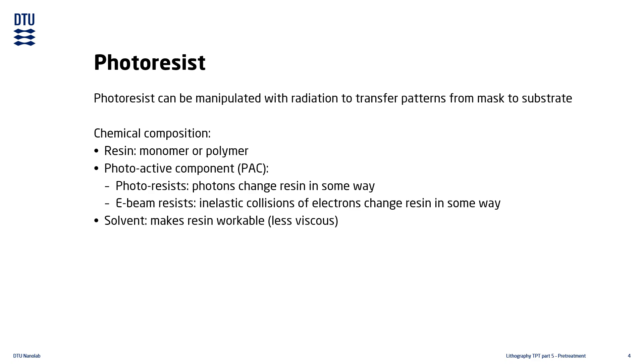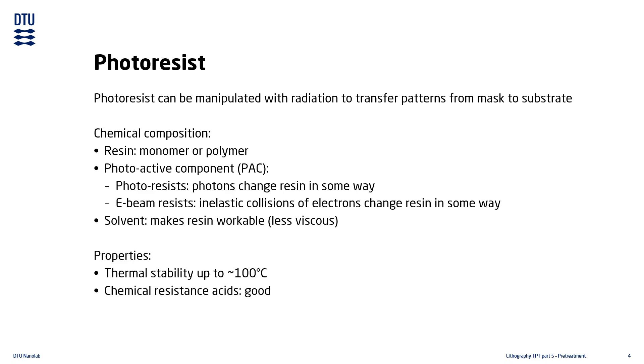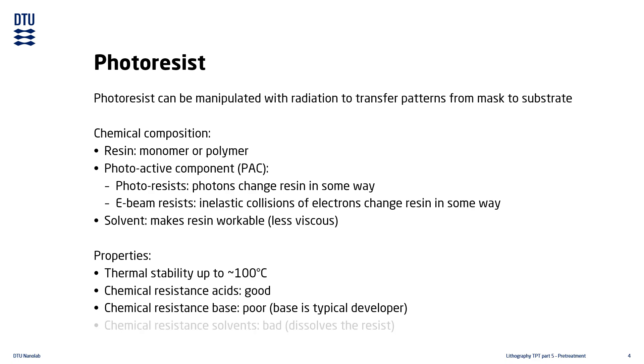The solvent is added to dissolve the resin, which makes it liquid and easier to work with. In general, resist films will be thermally stable up to approximately 100 degrees Celsius. Resist usually has good chemical resistance against acids and poor resistance against bases. Bases are often used as developer solution, which means that resists are often designed to be etched under controlled circumstances by alkaline solutions. Most resists have poor resistance towards solvents, because solvents are already used for dissolving the resin to make it liquid, and treating a resist film with solvents would simply dissolve the film.